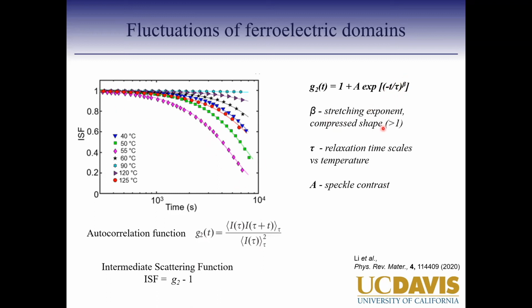And then beta would be the stretching exponent or the compressed shape, which is what we see in this case. So if you just had exponential dynamics, normal diffusive behavior, beta would be 1. It will just fit an exponential decay as your material is fluctuating. But the fact that beta is greater than 1 means that the material is actually jammed in a certain state, and then suddenly as the stresses or whatever is causing that pinning or jamming in that particular state gets released, the material then fluctuates into a different state and then continues that process. So that gives you sort of faster than exponential, more of a compressed state.